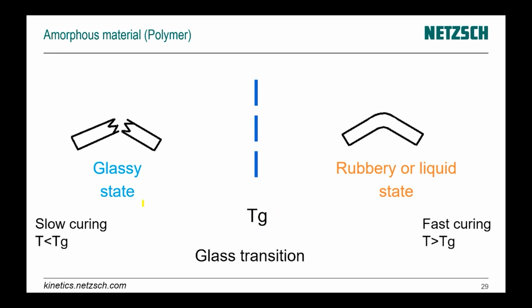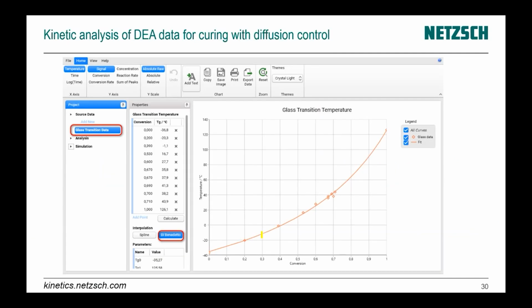And if we are below the glass transition, then curing can slow, and we must use the slow kinetics for the process, because we are below the glass transition, and above glass transition, the kinetic is different and the curing is fast. The problem is that the glass transition is not always at the same position. For an uncured material, it has the low value, and then during the reaction, it is changed from the low value to the high value. And now for DEA and for rheological data, we are able to put the glass transition data here from lower temperature for uncured material to the upper value for the cured material. Here is a temperature as a function of degree of conversion, which is changed from 0 to 100%.